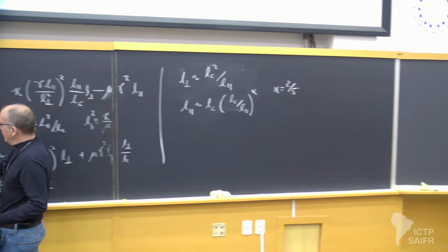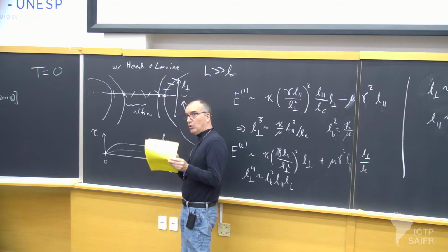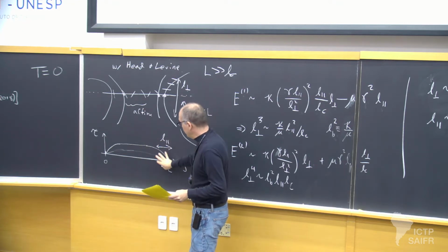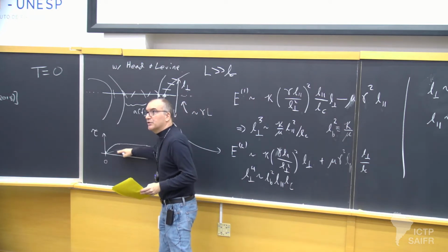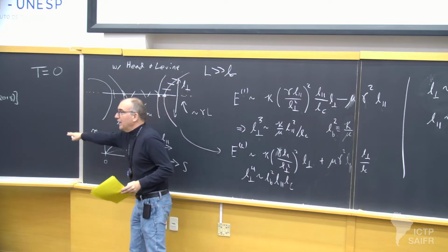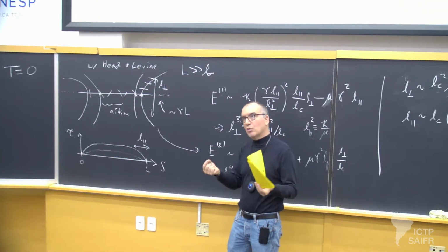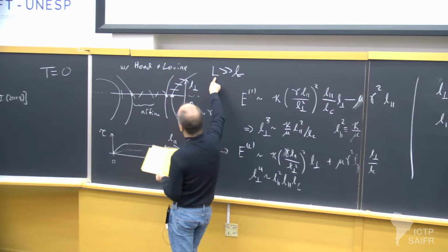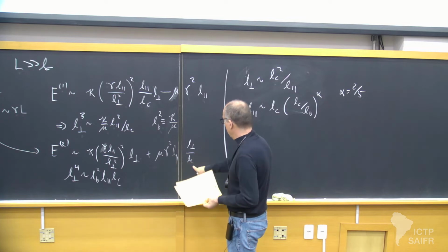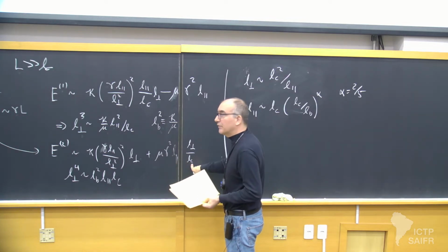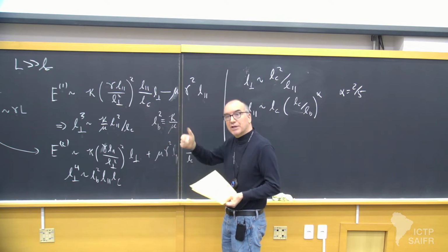Okay, now this is a general thing we should have expected, right? I'm claiming that a new fundamental length is going to come out of my network structure. If you accept that that's a local quantity, why do I say it's local? Well, if this stress relaxation is occurring right near the ends, independent of some affinely stretched region in the middle, if I double the fiber, this bit should remain the same, right? So it's something I should construct from local quantities, not a non-local quantity like the length of the fiber. And so the only length scales I have running around really are LC, the architecture of the network, and LB, what I get from my two parameters, stretching and bending.